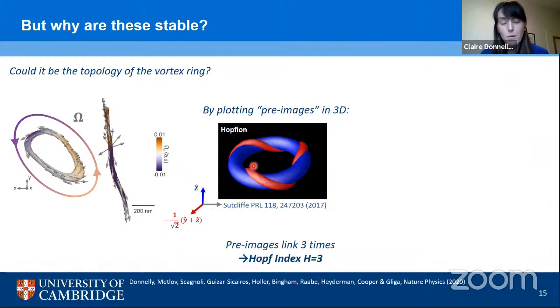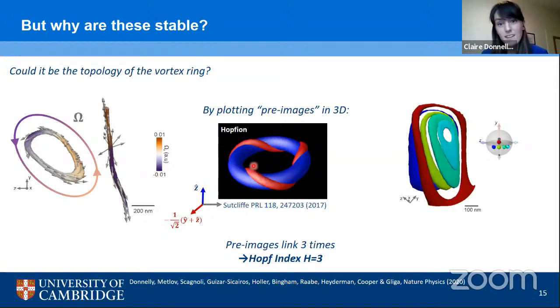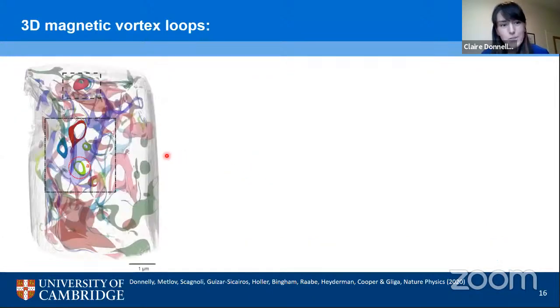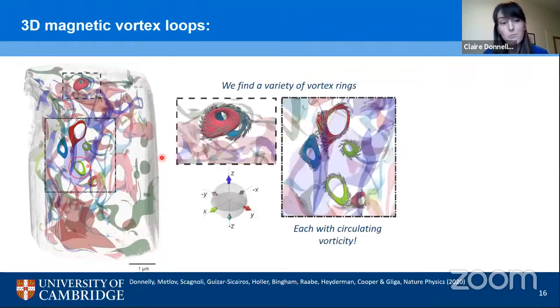So we can then go on to plot the pre-images for our own data. Now, almost unfortunately, we see that our pre-images do not link. So this is not a Hopf field, and it has a Hopf index of zero. However, this is even more intriguing. We have this 3D structure that shouldn't be stable, but it actually is. So we go on to look further into our data to see whether there could be more of these structures around. And indeed, we identify a number of these vortex rings, each that have this circulating vorticity vector.